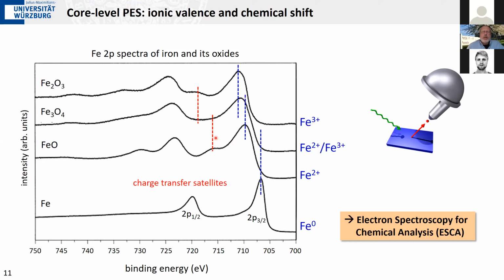Here, for example, this is the charge transfer satellite that you see typically for divalent iron. For trivalent iron, as here in Fe2O3, it has a different energy relative to the main peak. And so these characteristic charge transfer satellites can be taken as fingerprints of the actual valency. In fact, here in magnetite, which is of mixed valent nature, the spectrum that we see is simply a superposition of the divalent and the trivalent spectrum that we see in the FeO and Fe2O3. So that's something you can also utilize in order to extract chemical information from your core level spectrum.